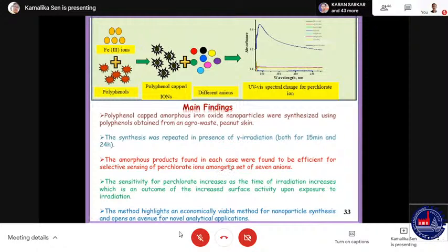The amorphous products found in each case were found to be efficient for selective sensing of perchlorate ions amongst a set of 7 ions. The sensitivity for perchlorate increases as the time of irradiation increases, which is an outcome of increased surface activity upon exposure to irradiation. The method highlights an economically viable method for nanoparticle synthesis and opens an avenue for novel analytical applications.